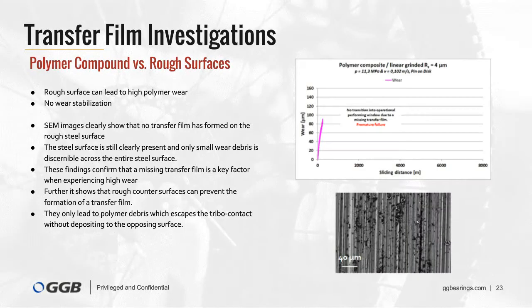Previous results showed also that rough surfaces lead to an enormous increase in system wear. An increase in roughness heights can lead to an increase in abrasive-induced wear, especially when a softer material slides against a harder and rough counterface. Abrasive-induced wear is seen as a critical wear mode for polymer-based materials. We also speculated that a rise in wear is a result of a missing or an insufficiently formed transfer film.